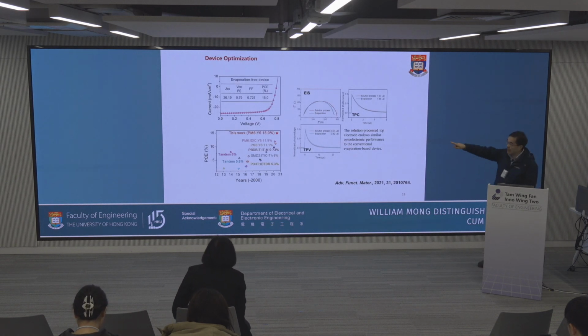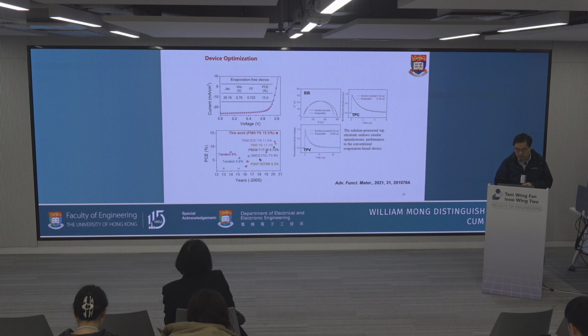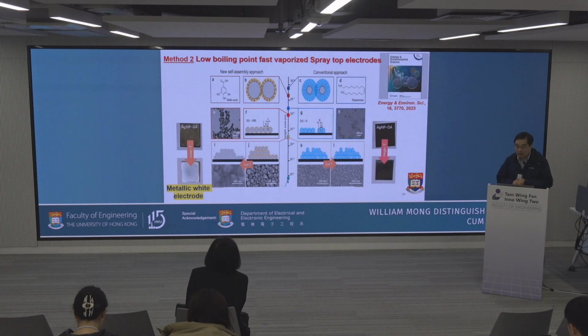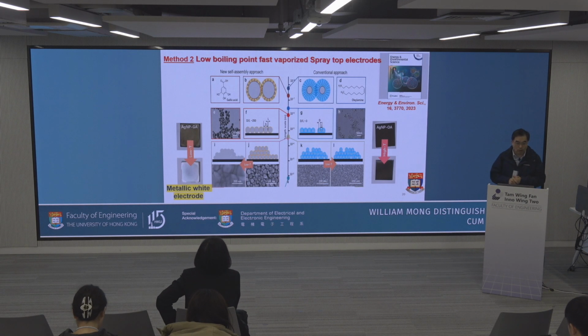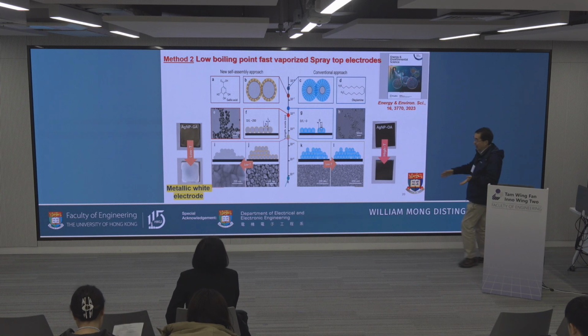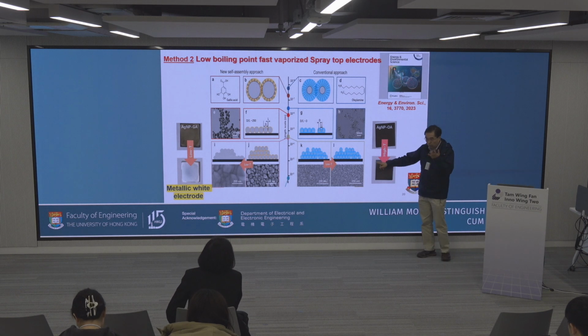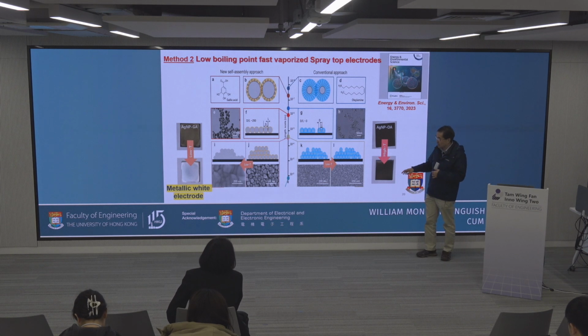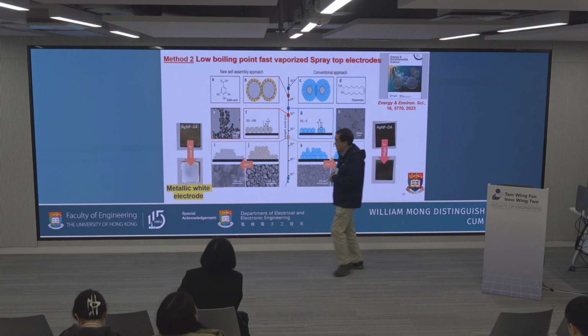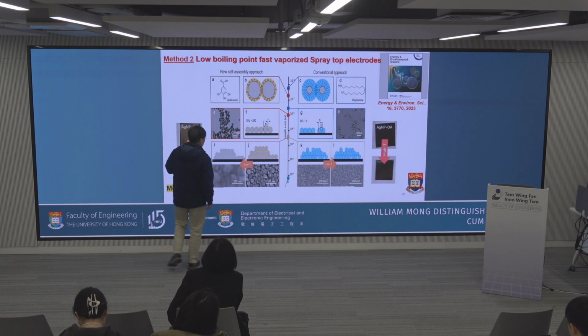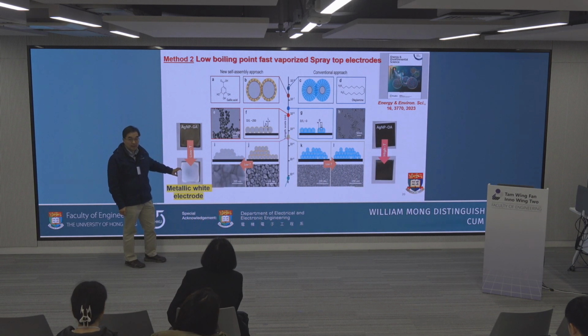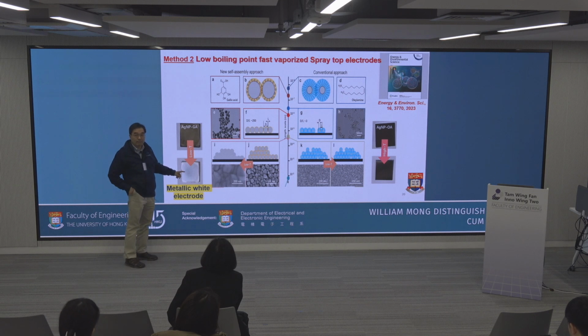This is the OPV we demonstrated at that time with a truly solution process top electrode. Next, we recently developed this metallic white electrode. Every morning when we wake up, we look in the mirror and see our face, whether it is in good shape or not. But a true reflection, if it is good, should be white. This is the white electrode that we make in our lab. It is pure silver, 99.99%, but it behaves white, so it can reflect all light.